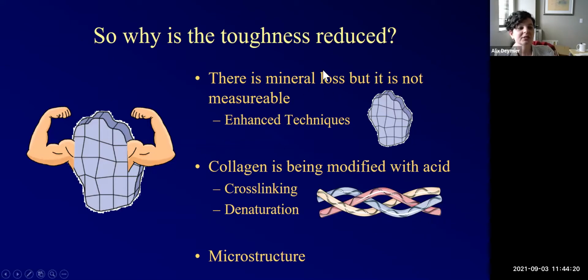Possible theories are that there is mineral loss, but that our Raman techniques that we're using now are not accurate enough to measure that small mineral loss, and that it may actually be enough to cause a change. Another is that maybe the collagen is being modified. When you work with composites, it's so easy to completely ignore one of the phases. But the collagen could be cross-linking or losing crosslinks. It could become denatured. Denatured collagen is jello. That would mean turning something that's got the stiffness and toughness of skin into jello, which would be mechanically very affecting. Or maybe it's something to do with the microstructure. We do have pores filled with fluid, right? 10% fluid. The size and orientation of those pores at the micro scale, which we didn't measure, might be modified, which could create little stress concentrations or little tortuosity pathways, which could limit the crack propagation.